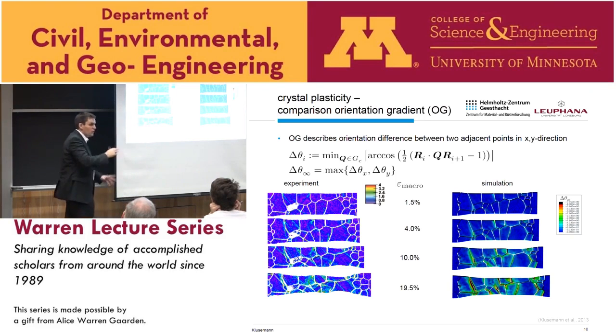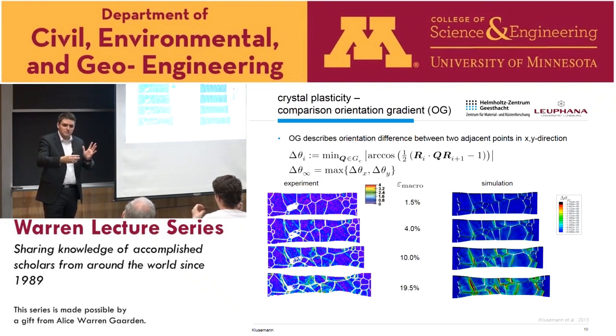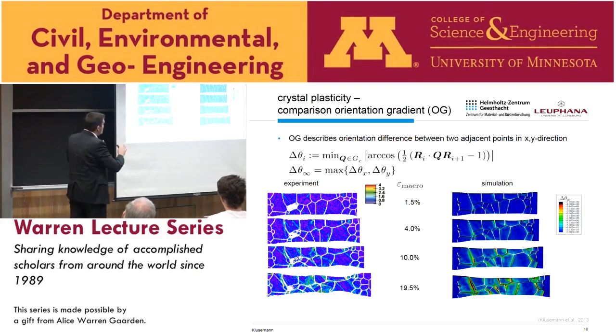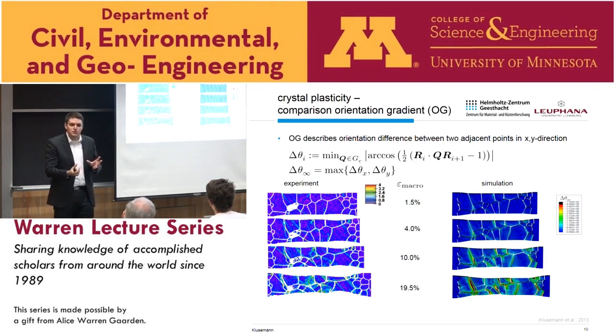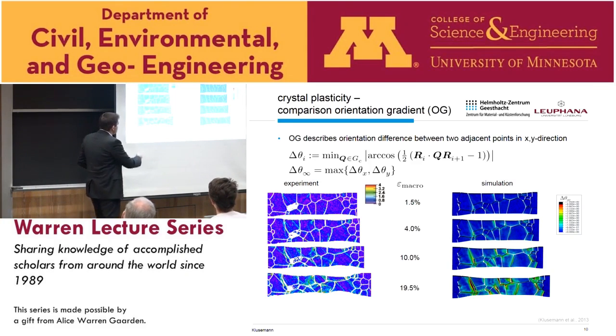And then of course you minimize that with respect to all crystal orientations, and you're plotting here the maximum in x and y direction. Simply on the surface you can do that. At least in the experiment simulation we can do volume-wise, but we compare here only the surface one. So on the left you see the experiment, and what you can see in particular is that we have some local regions where large orientation gradients appear.